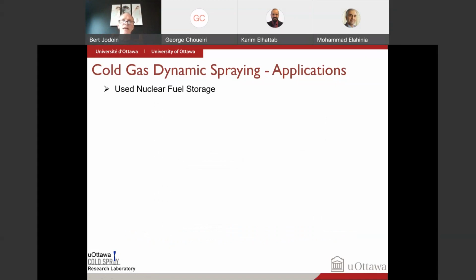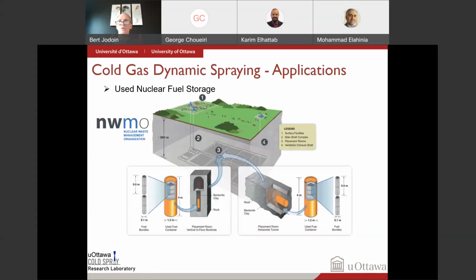Quickly, before I end, another application is used nuclear fuel storage. This is in partnership with the Nuclear Waste Management Organization. So in Canada, what we're going to do with our nuclear waste, we're going to get the used fuel bundle. Just like everybody else, we put them in a steel container, and then we apply a copper coating on top of the steel container, and we dig a hole 1 kilometer down or half a kilometer down in the Canadian Shield, and we're going to store them there in bentonite. And we need to have a copper coating because copper has been shown to be very, very stable when you put it in the bentonite clay.